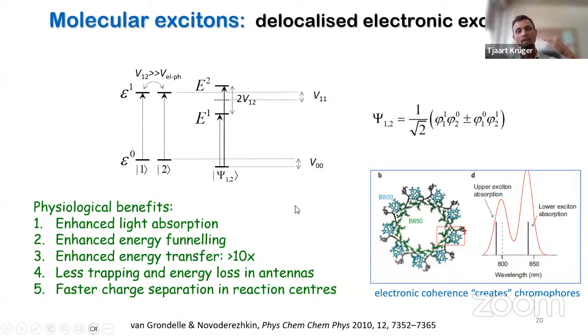So now one gets an exciton manifold, and because of the coupling between these excitons and phonons, excitations will be concentrated mostly into the lowest energy states. Okay, and this is different from a classical system. So classically, one would use an equipartition where the likelihood of population of each energy level will be equal. It's different for a quantum system. Thirdly, there's enhanced energy transfer. So more than 10 times, and this can be modeled quite easily.